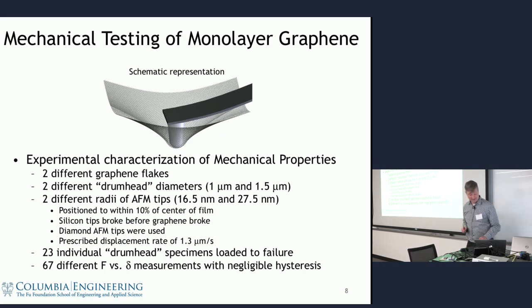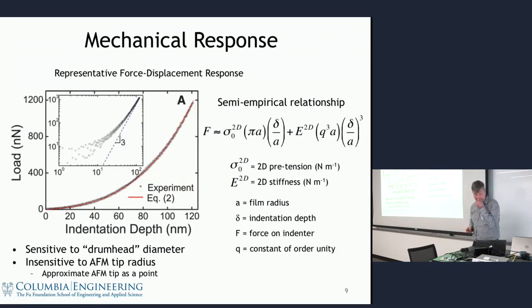Okay, so we got a lot of data. Here's what this data looked like. This is one of the first plots from the paper. We see a force displacement curve, in nanonewtons and displacement depth. You can see a curve that looks kind of like this, and you notice that as you get to higher displacement, it approaches a cubic term, right? This is on a log-log plot, so you can see this looks like a linear transitioning to a cubic behavior, right?